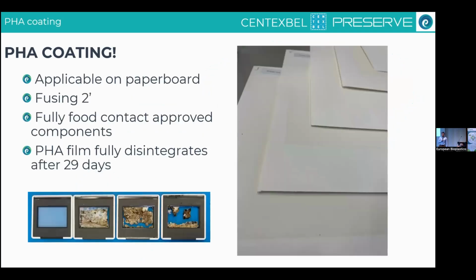Now then, for some of the properties and the details: this PHA coating is applicable on paperboard. That is, of course, quite important for this project. We are able to fuse this material into a coating by heating it for only 2 minutes. This solves a lot of the thermal degradation issues that PHA has, because with only 2 minutes we can obtain a nice and homogeneous layer. Since we're working with food contact materials, all the components that we use within this PHA-based coating are food contact approved. And initial evaluations show that this coating fully disintegrates after only 29 days.